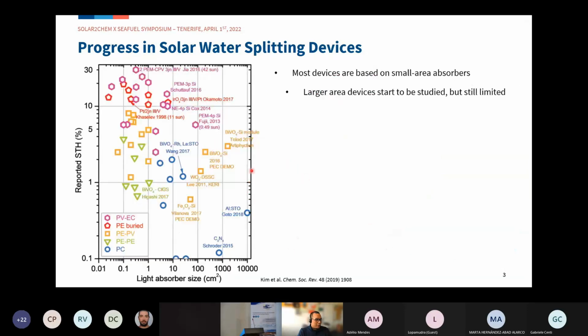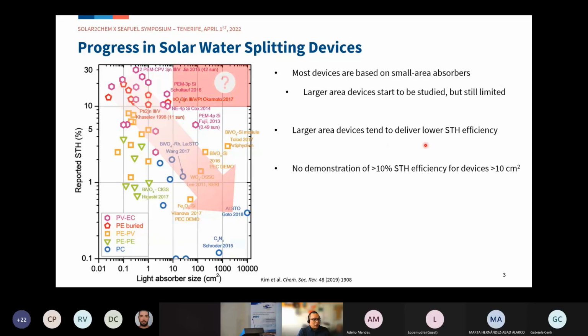From the same review, we have another plot, just a different way of representing the data. Now the solar to hydrogen efficiency is plotted as a function of the absorber size. And from this, we can see that most devices, or a majority of devices, are based on small area absorbers. But like Adelio mentioned, larger area devices also start to be studied in recent years. And the other thing that we can take a look at here, bear in mind that this is logarithmic, right? So larger area devices tend to deliver lower solar to hydrogen efficiency. And the situation is such that if you take a look at the top right-hand corner of this plot, we do not have any demonstrations of devices that show more than 10% solar to hydrogen efficiency and an area larger